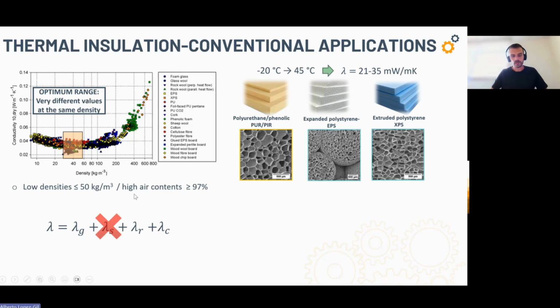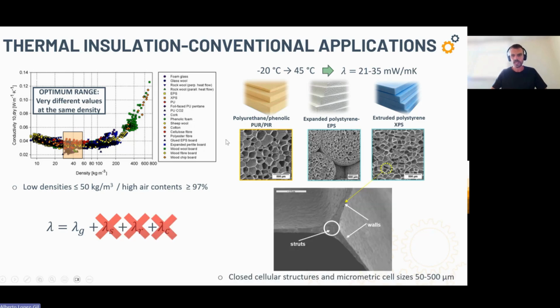And by doing this, we suppress the contribution of the solid material to the thermal conductivity. This is the thermal conductivity of a material, which is composed by the thermal conductivity of the gas phase, the solid phase, radiation, and convection. So by increasing the air content, by reducing the density, within this range, we can suppress or reduce a lot the contribution of the solid polymer, polystyrene, polyurethane in this case. And moreover, these materials are designed to be closed cell and to have cell sizes within this range, 50, 500 microns. And by doing this, we can also suppress the radiation term and the convective term. So in the end, we have basically the thermal conductivity of the gas, which in this case is air.